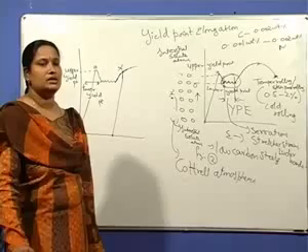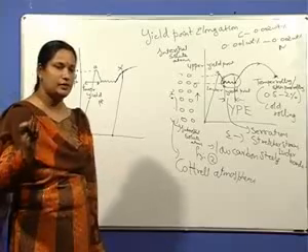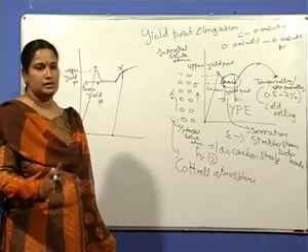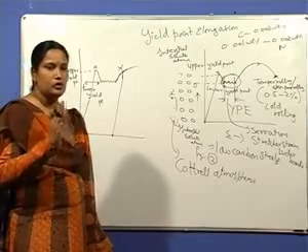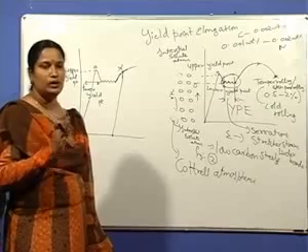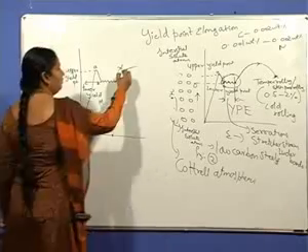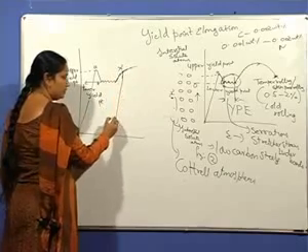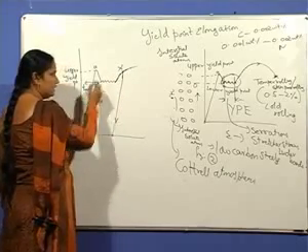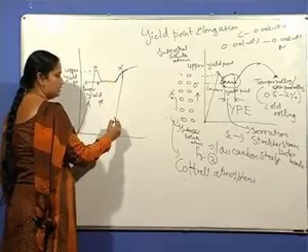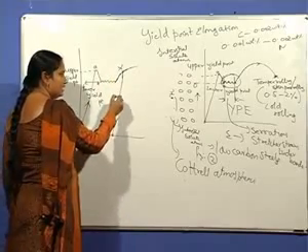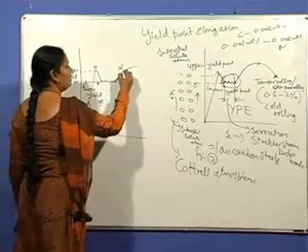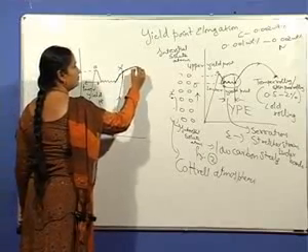Why? Because the dislocations have completely torn out from the atmospheres. So there are no atmospheres to lock the dislocations, and no serrations, no Luder bands, no stretcher strains are seen. When the material is loaded to the point X, unloaded, and again reloaded immediately, the curve normally follows the same path.